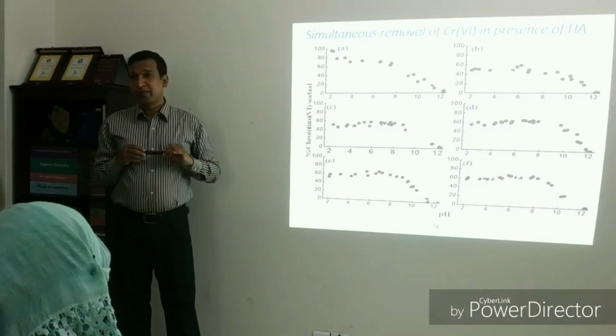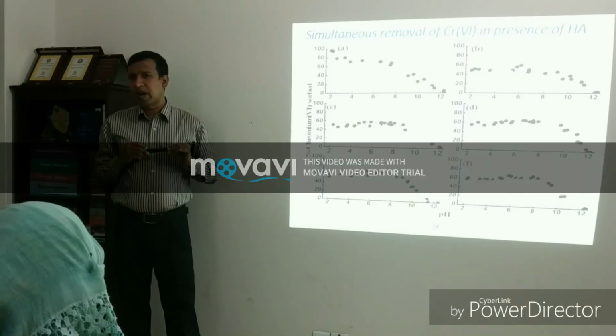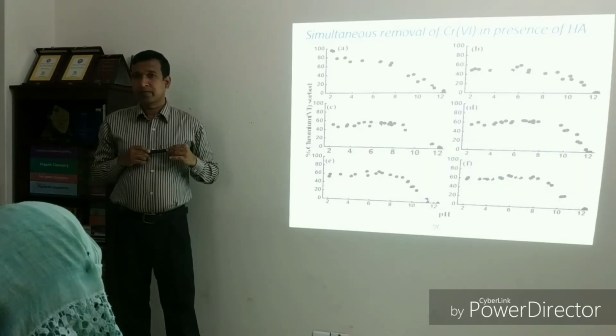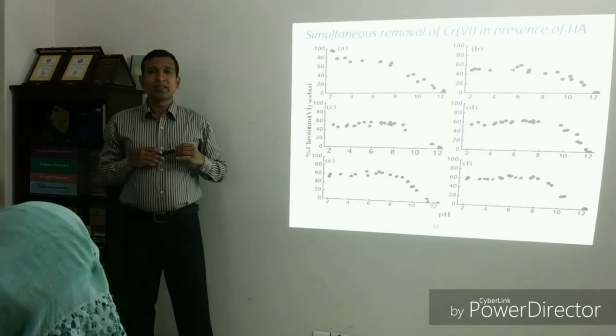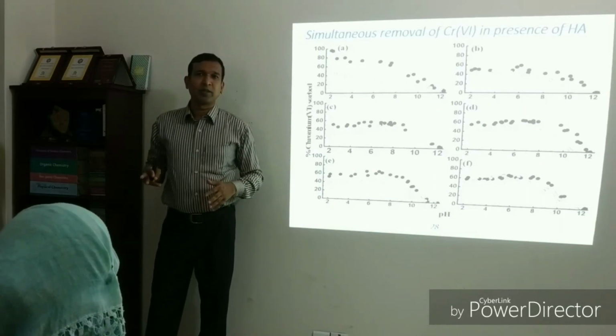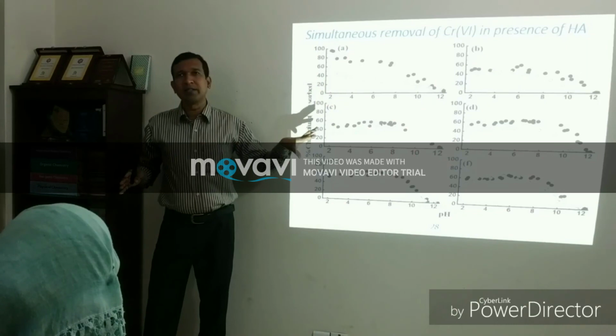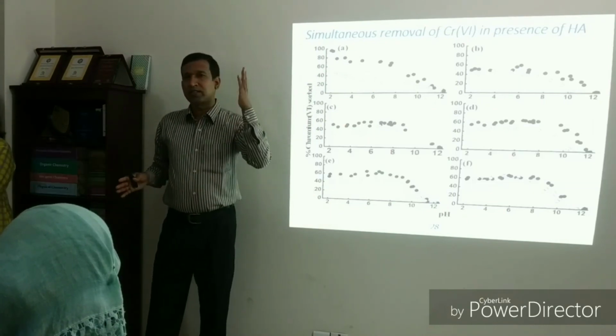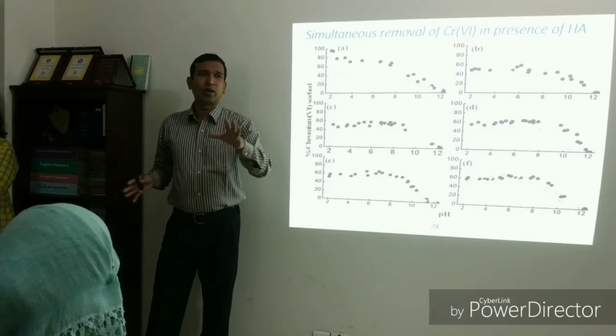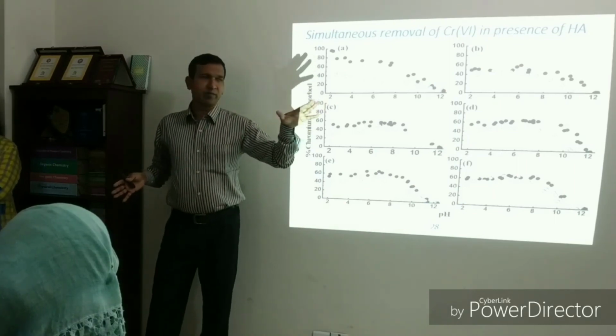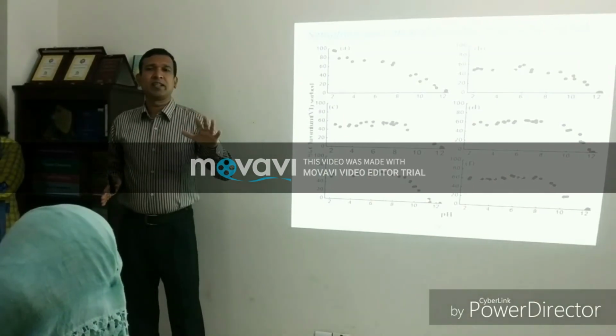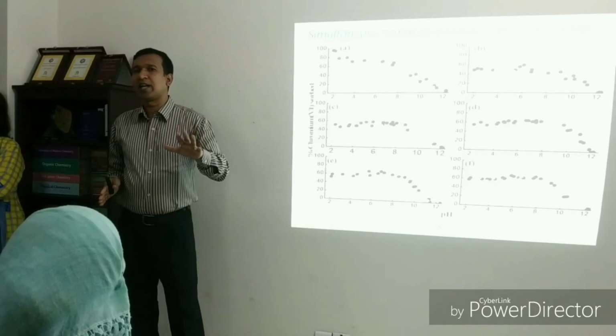If we compare the adsorption between graphene and graphene oxide on the adsorption process, what is your assumption, in which will adsorption be higher? You can't predict now without characterizing the surface properties, because the surface properties of manganese oxide and boehmite are completely different from graphene and graphite oxide. It will depend on the specific surface area and point of zero charge. That's why I tell several points in various conferences that before studying any surface as an adsorbent, please characterize the surface in terms of specific surface area and point of zero charge.